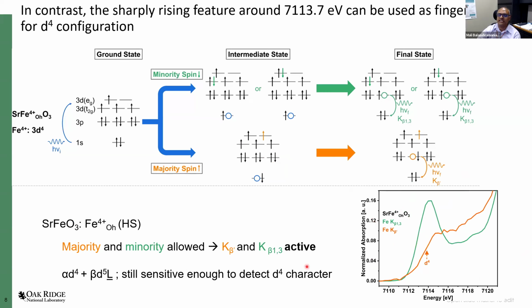On the other hand, if we do the same sort of thought experiment on this 3D4 configuration of iron 4+, because we now have an empty state that is available in the 3D manifold, one can populate that with both a minority spin as well as the majority spin. So this gives rise to emission, which would have both the K-beta 1,3 channel as well as the K-beta prime channel become available. And thus, both the minority and majority spin state as seen through these channels, K beta prime and K beta 1,3 become active.